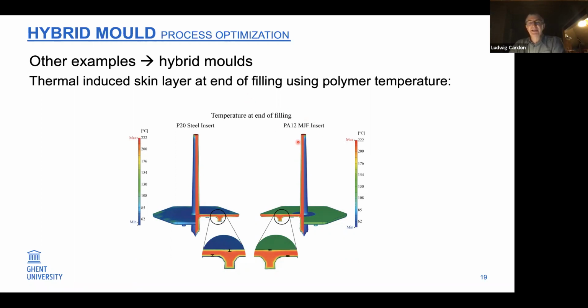When we then inject inside a plastic mold, we notice the green means it's not yet fully cooled down. So we notice that the temperature of your skin layer is a lot higher. So the crystallinity and the whole morphology of the polymer you inject is finally completely different.